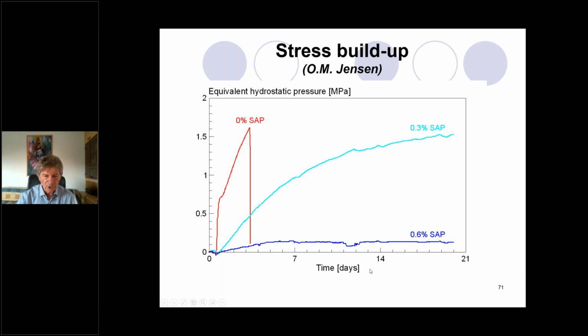And this is a very important issue, mainly for high strength concrete, for high performance concrete, which is made again with a very low water cement ratio. This concrete, as you may remember, was developed by the Japanese in the 1980s, immediately after they developed the first superplasticizers, and then it was possible to go very, very low in water cement ratio. But in the beginning, let's say the first 10 years, all the scholars, researchers and engineers were so excited about having this high strength concrete that only 10, 15, 20 years later did they understand that they have a problem of autogeneous shrinkage. This is extremely important to understand.